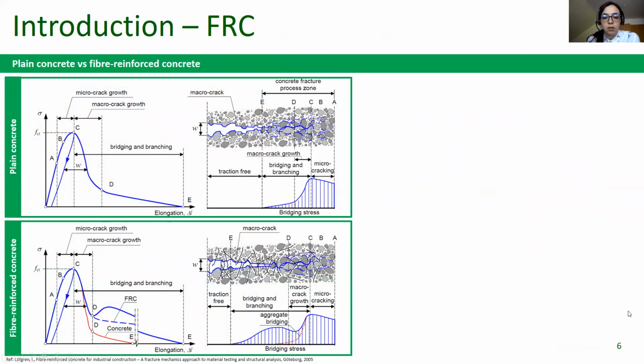In hardened plain concrete, microcracks pre-exist even before any stress is applied, mainly due to shrinkage and thermal deformation. When a tension is applied, the microcracks start growing at the weakest link of the composite, which is the aggregate-matrix interface. The microcracks start growing and propagate in an unstable manner until crack localization. In plain concrete, only aggregates can bridge the crack.